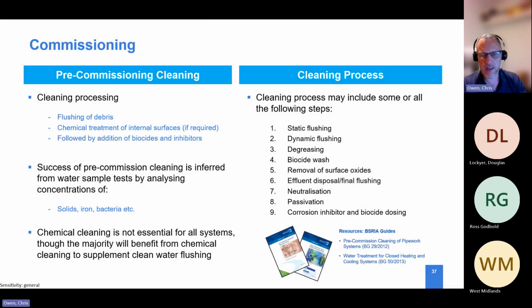And again, commissioning can be a CPD in its own right, quite a complicated, complex subject. However, we know that most of the processes involve some sort of flushing out of the debris, which is good because debris, as we've seen, can cause corrosion mechanisms. The chemical treatment of the internal surfaces as part of a cleaning process can be quite beneficial in terms of removing any debris or internal scale which can contribute. However, thin wall tubes are supplied with an internal protective coating, and the problem is that the chemical treatment taking place to clean the tubes was actually stripping off that coating, leaving the exposed virgin metalwork open to the elements, and that was again initiating corrosion.